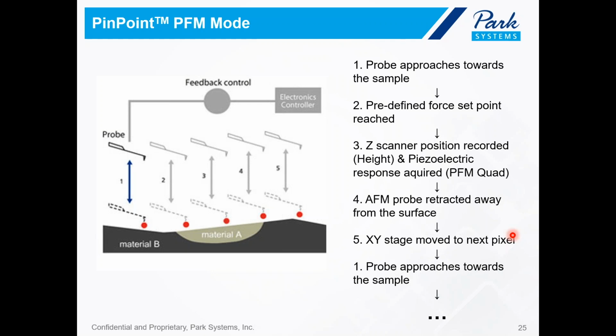So PinPoint PFM really allows for higher spatial resolution with optimized piezoelectric response measurement over different sample surfaces. No matter whether your sample is very flat or very rough, PinPoint PFM will prevent the tip from scratching the sample. PinPoint PFM was designed to replace the conventional contact PFM, and it's an enhanced design that eliminates the problem of the tip wearing out during contact mode topography and diminished contact time. The PinPoint PFM technology has proven to solve the majority of the shortcomings of conventional PFM, including quick tip wear, degradation of resolution, poor signal-to-noise ratio, and poor reproducibility.